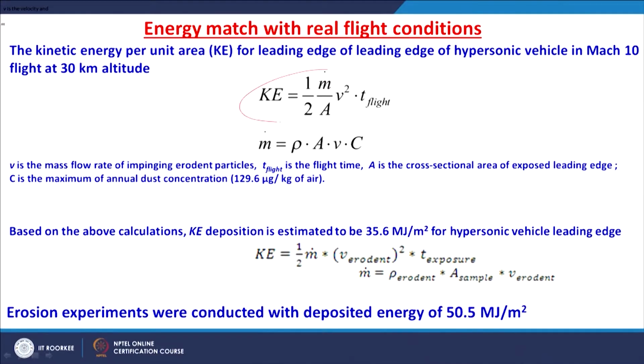We see the kinetic energy per unit area for the leading edge of the hypersonic vehicle flying at Mach 10 speed at 30 kilometers altitude. The kinetic energy can be estimated if you know the flight time, the cross sectional area of the exposed leading edge, and the mass flow rate of the impinging erodent particles, where this m dot can be found out from density, the cross sectional area of the leading edge, the mass flow rate of the particles, and C, a constant. Generally C max is the maximum annual dust concentration, which was taken as 129.6 microgram per kilogram of the air. This was taken from the literature.